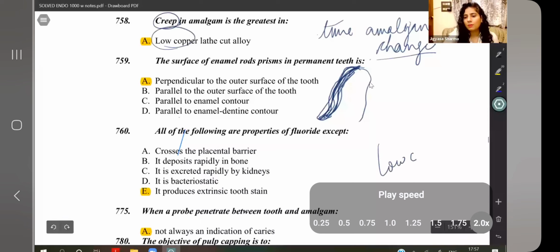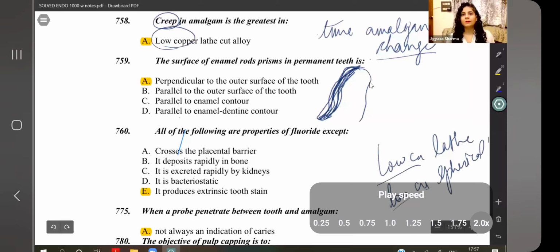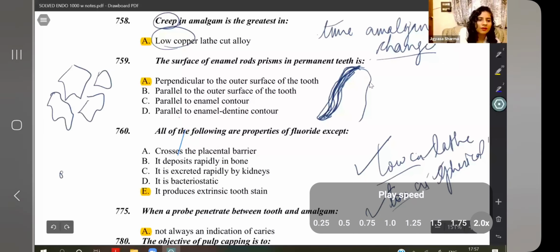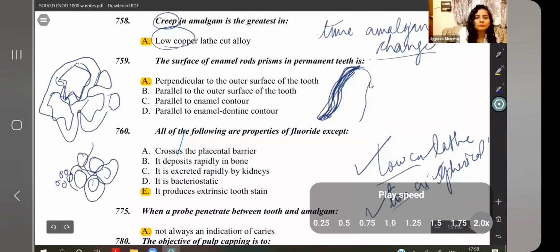If you have the option of low copper lathe cut and low copper spherical, how will you pick between? Both have low copper. Now which has less mercury amongst these would be more resistant to creep. Which would have more mercury would be more corrosive, more prone for creep. So amongst the lathe cut and spherical, which requires more mercury to wet all the surface? Imagine you have this lathe cut, irregularly shaped, and you have spherical. Same amount of particles, just different shape. Where would you require more mercury to coat all the particles? Where you have more irregular surface, you require more mercury to coat it. Where you have uniform spherical surface, you require less mercury to coat that uniform surface. So spherical requires less mercury, lathe cut requires more mercury.